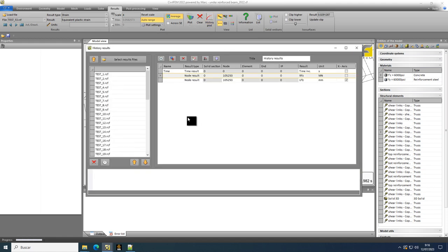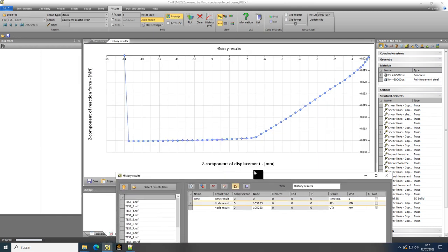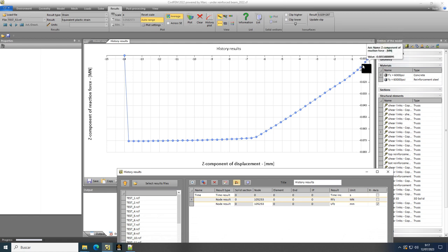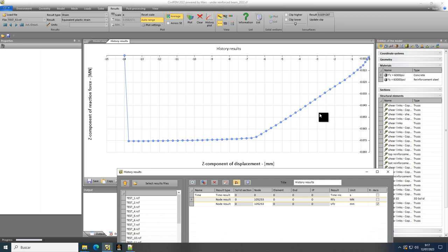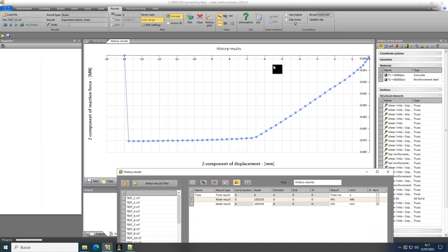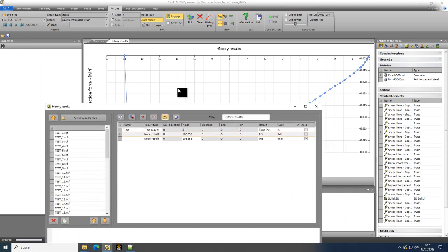Plotting vertical force versus displacement shows a clear behavior history: first, a linear elastic branch; then cracking starts, producing a lower-stiffness cracked section branch; then at a certain point yielding starts, followed by a plastic branch until failure. With this nonlinear model we can accurately determine load versus displacement, study the cracking point, identify when yielding starts, and confirm ductile behavior. This type of analysis can be very useful for research or forensic engineering.